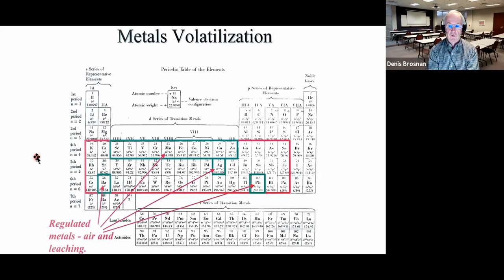Put them on the hearth of the kiln, fire them to various temperatures up to 1400 degrees Celsius. And the first thing I noticed was that when the kiln cooled off and I went in and took the little cylinders out of the kiln, I could see a halo of green material around where the pellet was sitting. I couldn't understand that. I thought, this must be surface diffusion of the chromium out onto the hearth of the furnace. Well, it wasn't. It was vaporization of chromium. So I know that now, but didn't know it at the time.